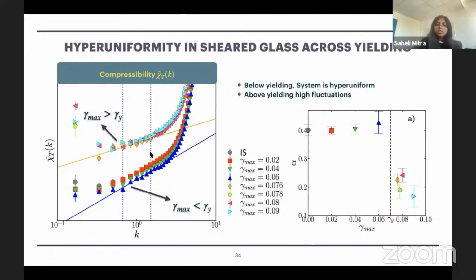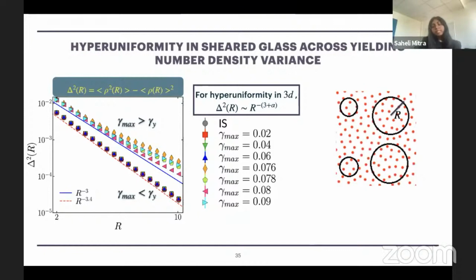So next we look into the hyperuniformity analysis from the real space number density variance. We put some observation windows and we compute the number density variance, rho square average minus rho average square. And for a system to be hyperuniform, this variance will scale as r to the power minus 3 plus alpha. We see that indeed for the cases of shear amplitudes below yielding, we have a scaling that is r to the power minus 3.4, and above yielding, my system is no more hyperuniform. So now we want to see what is happening above yielding.